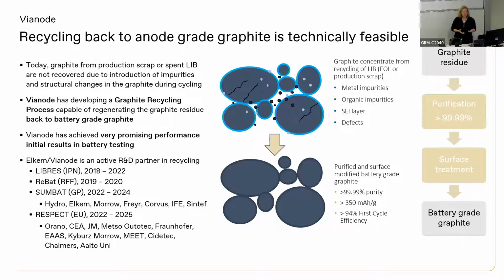And so what we see is that that is entirely possible to do. That with the processing that we have developed, we are able to take that scrap graphite and renew it into new anode material that works in exactly the same way that the virgin anode material worked, except then we're able to cut out an extra 40% of the CO2 footprint of that product, which, you know, it wasn't so much before because we've already taken 90%, but it's always nice to try to get that little extra bit at the end.